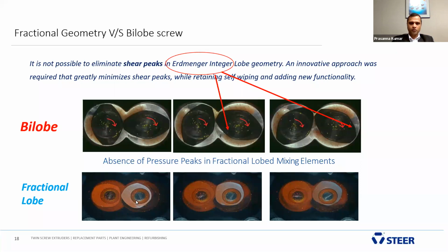With the fractional lobe, we can see the material getting conveyed from one lobe to another, and you see there is no material getting squeezed and coming in between the lobes. So this generates the fractional geometry. It generates uniform shear instead of peak shear, which helps in better dispersive or distributive mixing for many applications.